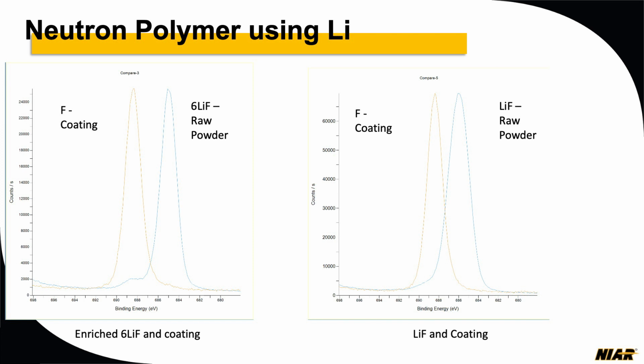Now the lithium, we didn't find anything on the top surface. So we definitely need to do a lot more work to actually find out where the lithium is visible right now. The coating is on top, no lithium, but we need to do a depth profile to actually find out where that lithium level is. Because lithium is very reactive, we have to go a little bit slow and not damage the coating system and still get a lithium signal.